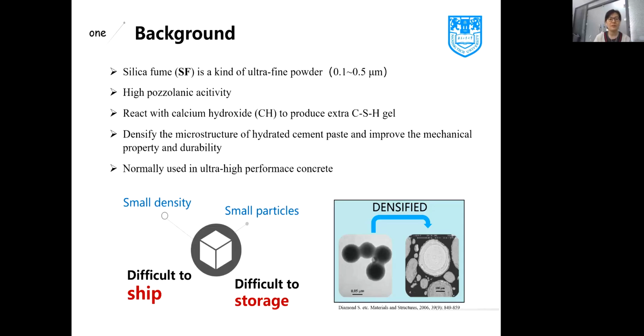As we all know, silica fume is a kind of ultrafine powder. It has pozzolanic activity. It can react with calcium hydroxide to produce extra CSH gel. It also can densify the microstructure of hydrated cement paste and improve the mechanical property and durability of cement-based materials. It's also normally used in ultra-high performance concrete.